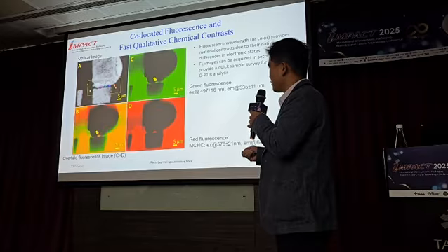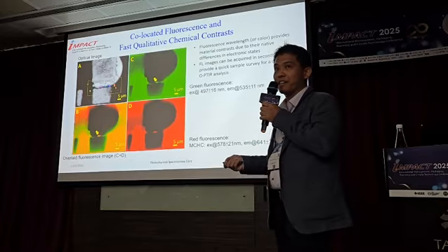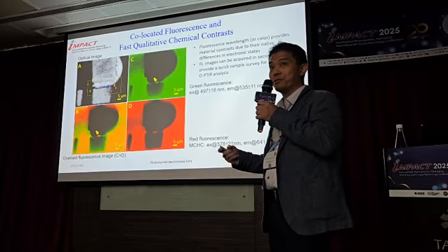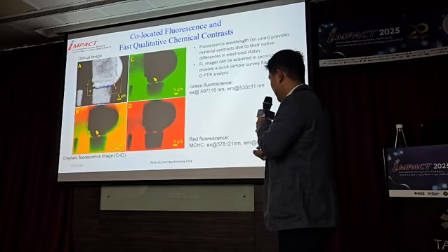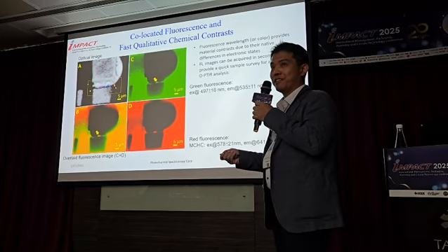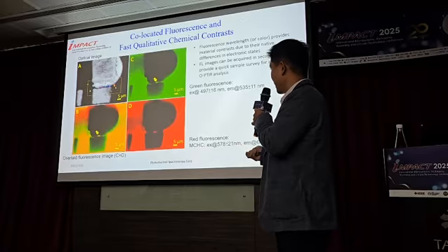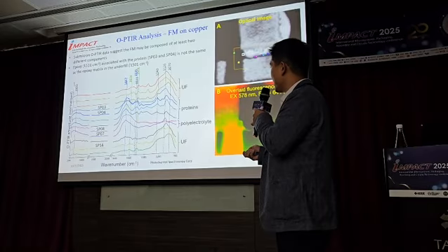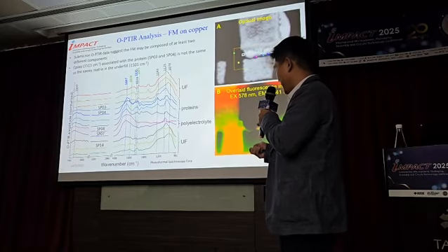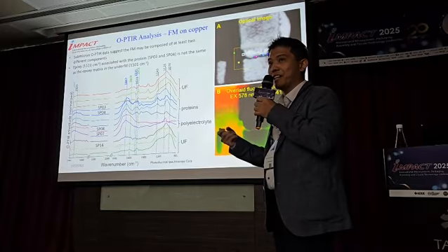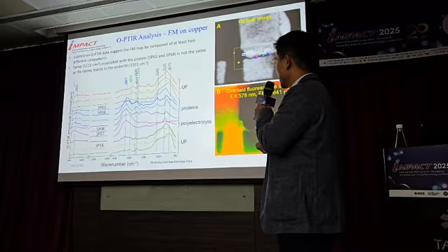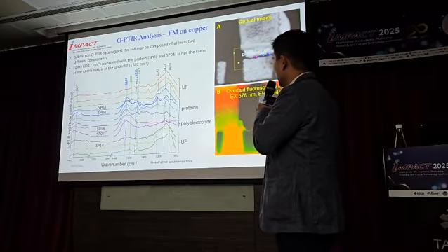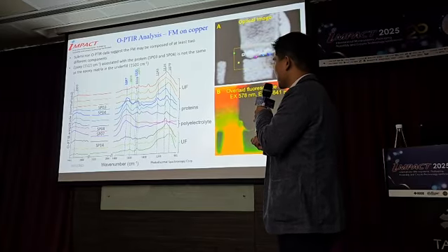And it does have a different color hue, so that tells us that there may be at least two different kinds of chemicals present. And this can all be done in less than 15 seconds, so that makes it a really fast, quick survey view. And finally, to get to the actual identification of the material, we point our laser beam right into that spot, and that will allow us to identify what this contamination is